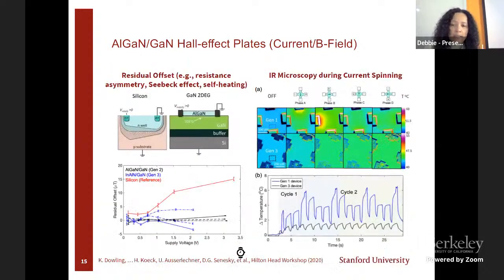And so this offset is something that my former student, now Professor Karen Dowling, studied. Wow, how do we mitigate this offset? So what's causing the offset is the thermal gradient across the device. And so that thermal gradient induces the Seebeck effect, and that's how you have the voltage. So just by powering up the device, you get a voltage offset. So that's through the Seebeck effect. Silicon has it as well. It's something you just can't really get rid of. And then any resistance asymmetry in your device through fabrication.